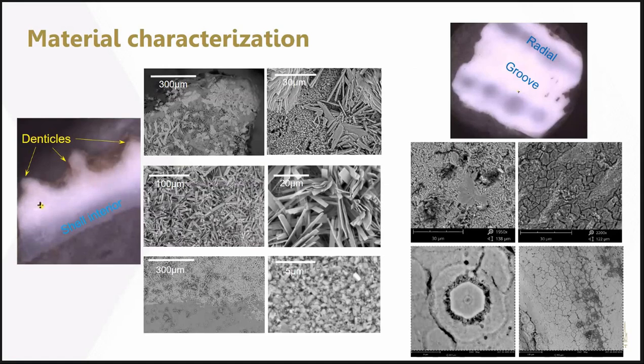Okay, so if we look at the material under the SEM, that's the profile view. That's the inside of the shell, and that's the outer side of the shell. These extruded points are actually part of the denticles. These are the SEM images at the top of the denticles. They have relatively smaller particle size and different morphologies. And these are photos taken in the middle section of the shell, and those are photos taken at the bottom